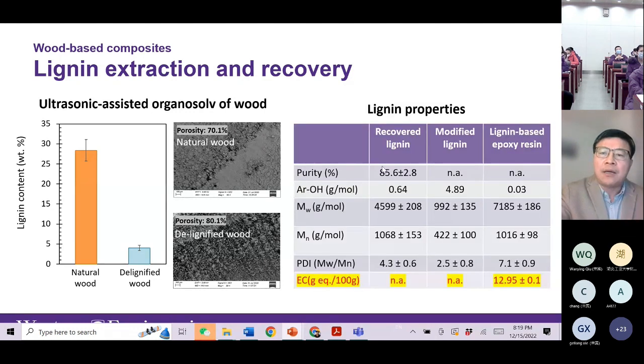And these are the lignin properties after characterization, for example, molecular weight, purity, and the epoxy content after we turn the lignin to epoxy resin. So we list it here. In terms of molecular weight, our original lignin has a number average of about 1,000. Then we turn it to epoxy resin, and the molecular weight does not change too much. Epoxy resin just epoxidizes the lignin functional groups to introduce epoxy groups into the lignin structure.